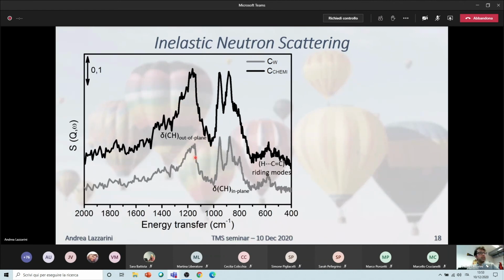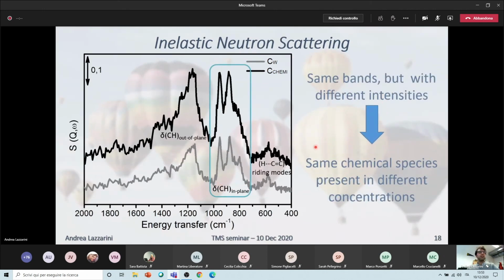So as you can see, they look pretty much the same. Of course, the intensity is different because of the surface area difference, because having a higher surface means that you have a higher number of hydrogen atoms. So they have the same bands and different intensities, especially in this particular spectral region, which is the one that gives us the information on the terminal hydrogens on the different borders, which can be more ordered or more disordered.